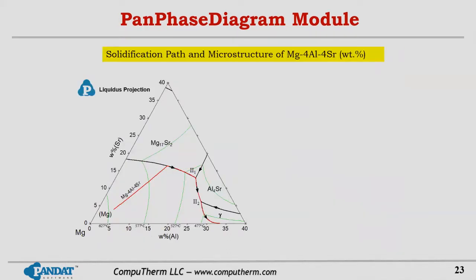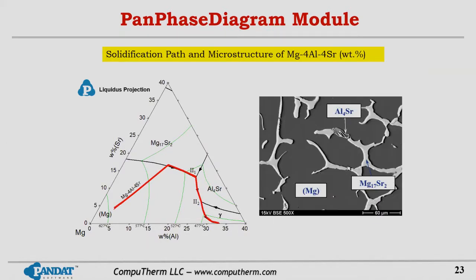For example, if you have a liquidus projection, in this case a magnesium corner, and you have an alloy and perform a solidification simulation, you combine the solidification simulation with the liquidus projection. Then you can see the solidification path and predict what microstructure you can get for this alloy during the casting procedure. This calculation is based on the Scheil model.